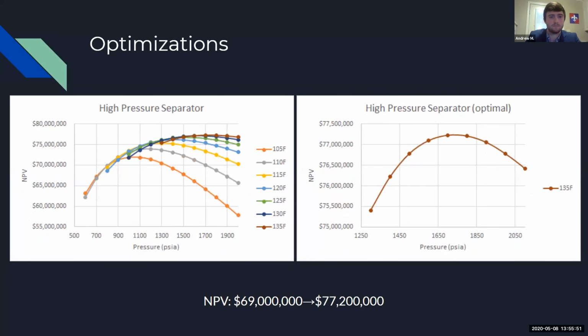And then for the high pressure separator, we coupled the pressure and the temperature. And after 135 degrees, the optimal pressure was higher than the reactor pressure. So we couldn't really go above 135 degrees. So we decided to cap it at 135 and then found our optimal pressure to be about 1700 PSI. And that brought our NPV from 69 million to 77,200,000.